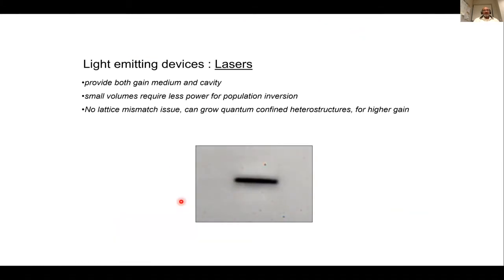So we take one of these nanowires, and if you shine light from the top, light starts coming from both ends of the nanowire, because the nanowire acts like a waveguide. The light gets reflected from both ends of the nanowire because there's a large refractive index difference between 3.4 of the nanowire and the surrounding medium of 1. So you can see I don't really need to put any mirrors or anything of that sort. If I design my nanowires carefully, every nanowire should act like a laser. That's what we are really trying to do: design and make a wide variety of lasers, for example.